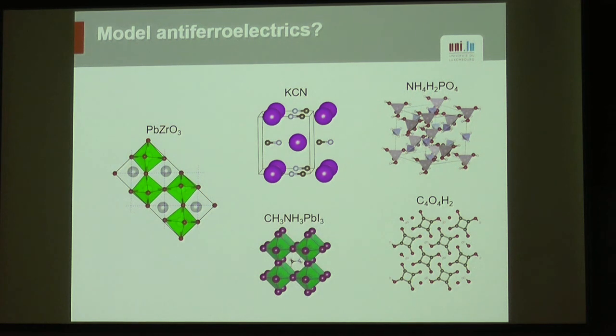There's been also some reports of antiferroelectric behavior or potential antiferroelectric behavior in those hybrid perovskites a bit more recently. And I like advertising for this squaric acid, which is one of the few examples that's been really nicely characterized at the experimental level with everything: the dielectric anomaly, the first principle calculations, and the field-induced phase transition.